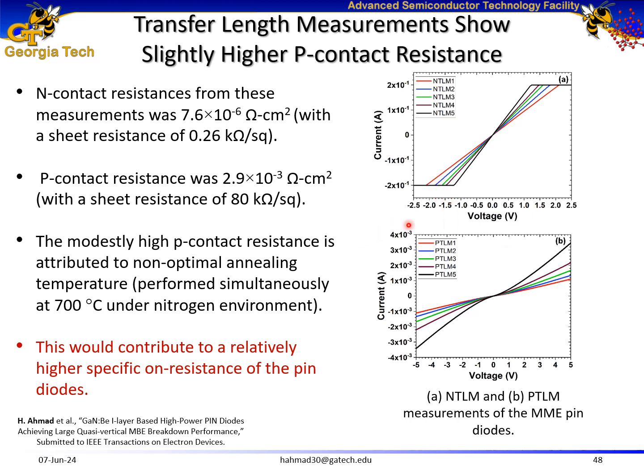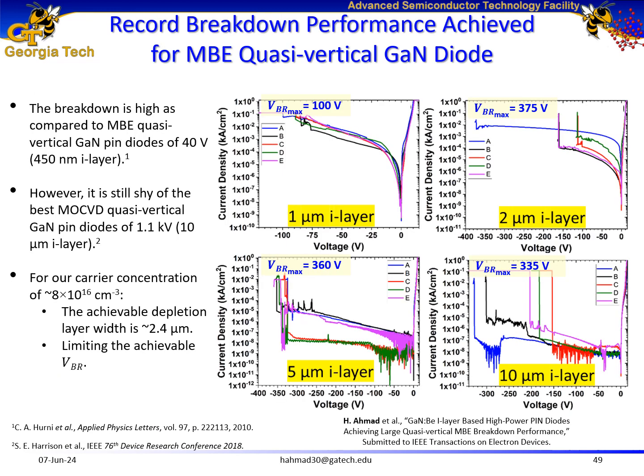From CTLM measurements, the n-type contacts showed contact resistance of approximately 8 times 10 to the power of minus 6 ohm centimeter square, while the p-type contact showed contact resistance of approximately 3 times 10 to the power of minus 3 ohm centimeter square. The p-type contact resistance is slightly higher because I performed the annealing of both types of contacts at 700 degrees C. So this annealing temperature is slightly non-optimal for the p-type contact, but this can be improved. However, in the current case, this would contribute to relatively higher specific on resistance of the pin diodes.